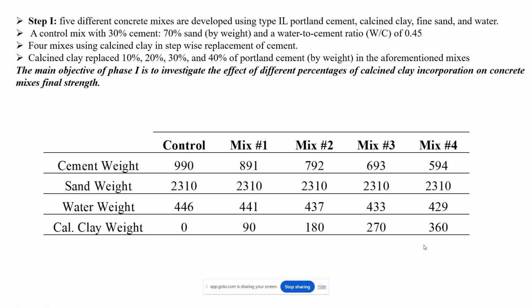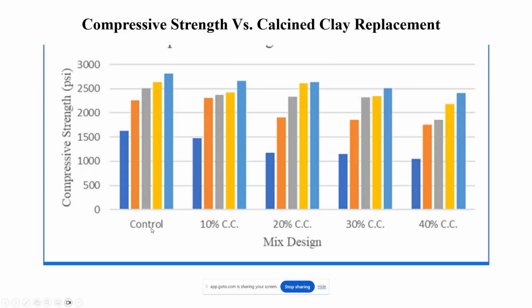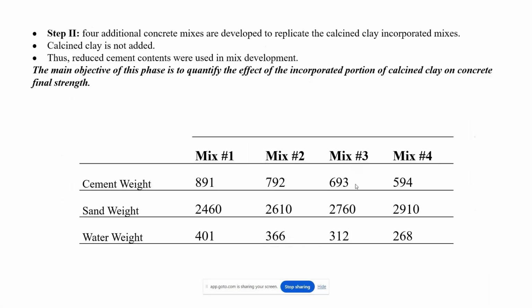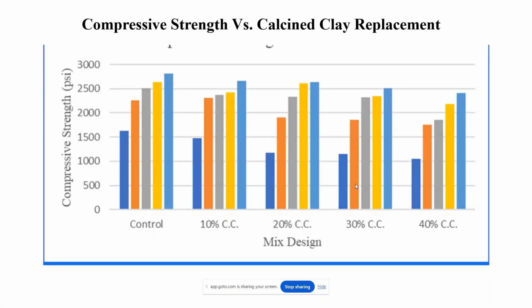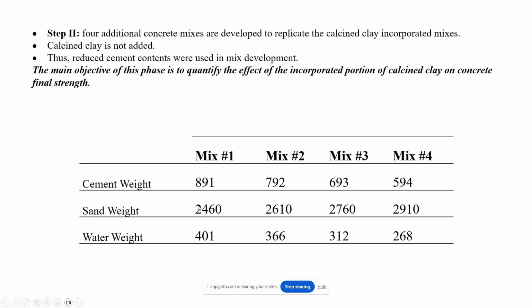almost 40% here. And we have done compressive strength testing for the control specimen, and for all the mixes up to 40% calcined clay. And we're here showing how the strength is looking at days 1, 3, 7, 14, and 28. So we can see that there is an acceptable rate, specifically if we talk about 20 to 30% calcined clay, the amount of effect on the strength is really minimal. Looking at this, it's probably less than 5% reduction, or even not that.